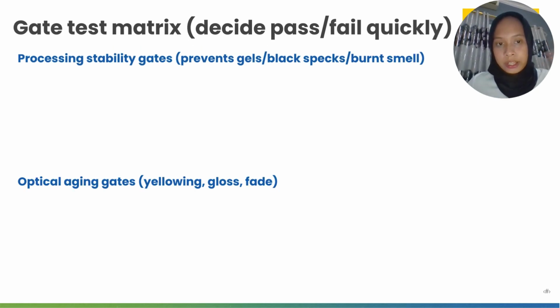Next, after we divide it into tiers, we create the gate matrix to decide if it passes or fails quickly. The first one is processing stability gates, which prevent gel, black speck, and burn smell. The test is residual moisture before extrusion, and the passing criteria typically needs low moisture and inline dew point, diagnosed by hydrolysis-driven degradation and gel.